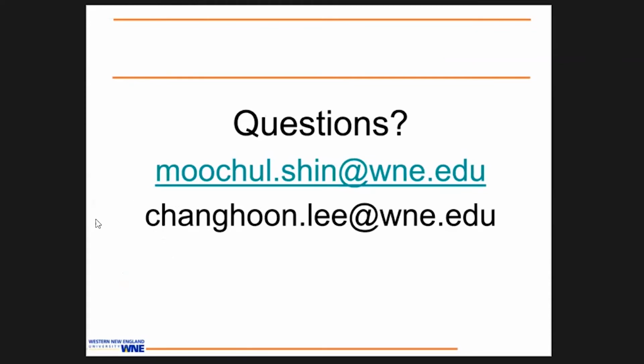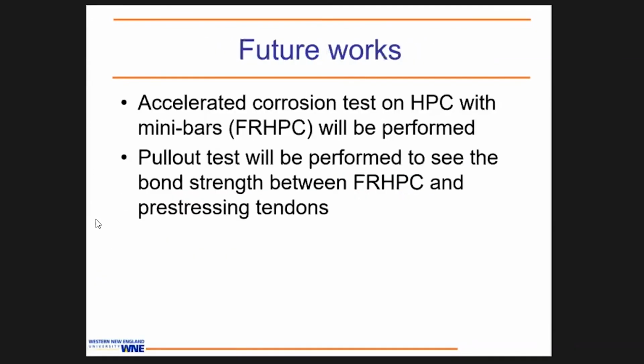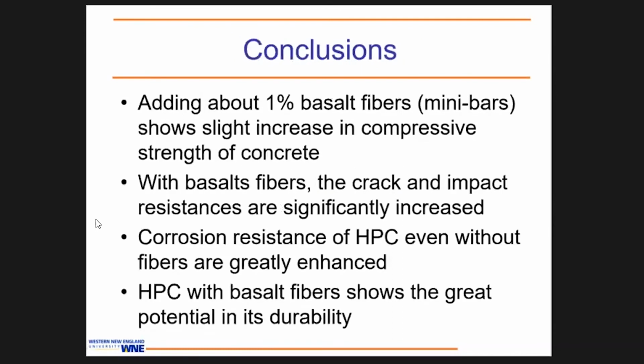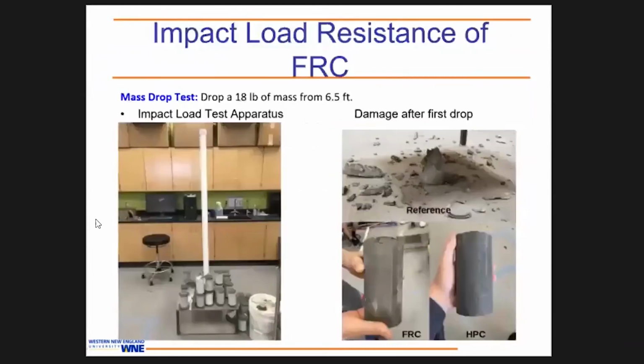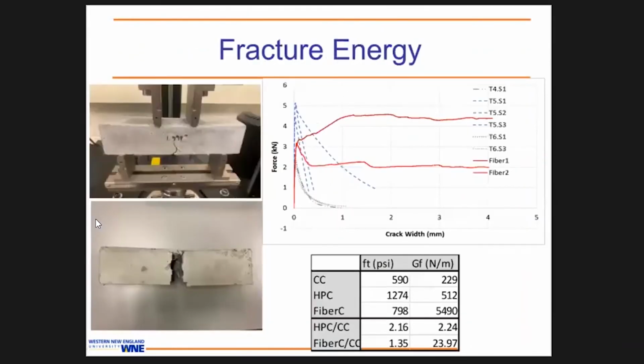What effect do fibers have on modulus? Oh, I don't think there will be a great effect on the modulus, but we haven't measured the modulus yet. We will be measuring the modulus together. I don't see that there will be much difference in the elastic modulus of the concrete in compression. It might also be noticed in the fracture energy test: the initial slope is almost identical between all three testing samples. So I imagine that there will not be much difference.